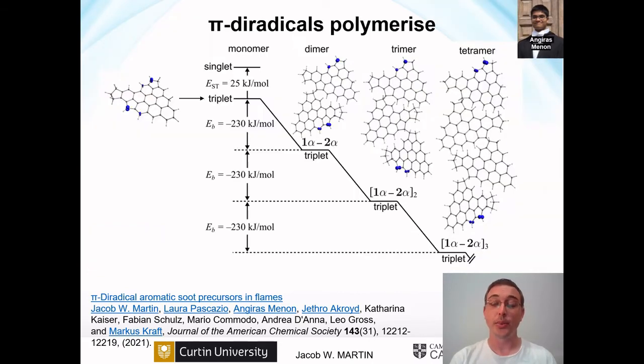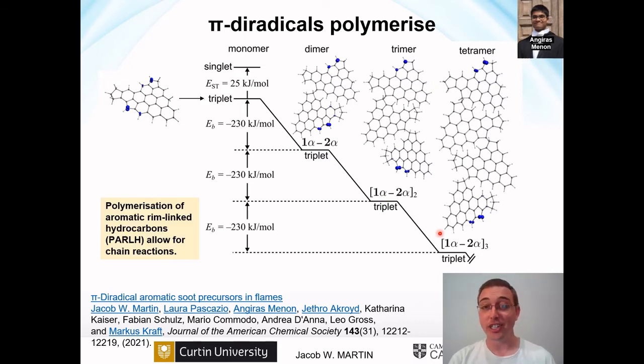So let me explore them a little bit more. What I mean by them being very reactive, and this I explored with Angiras, is that these are triplets and they actually react with no barriers, and the reactivity is maintained as the molecules cross-link. And therefore, what we actually have here is a chain reaction. So we're calling this the polymerization of aromatic rim-linked hydrocarbons, and it's the first kinetic mechanism that has this kind of chain reaction, which is critical for a rapid reaction to explain soot.